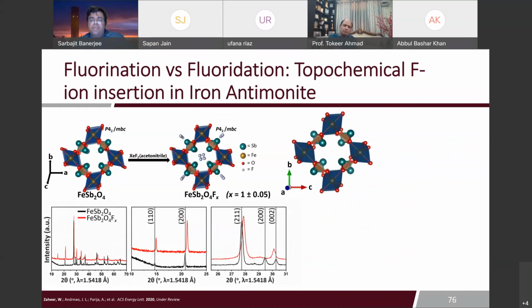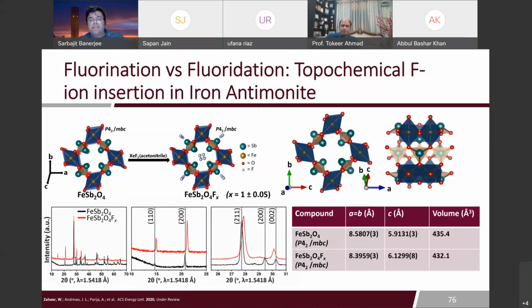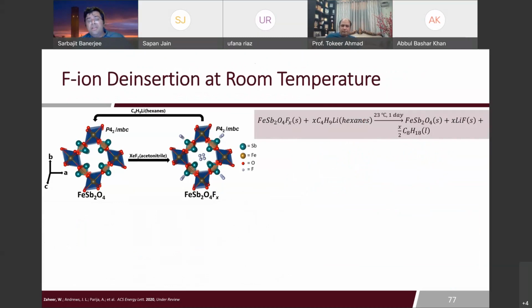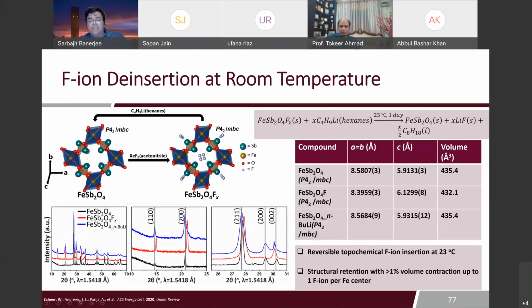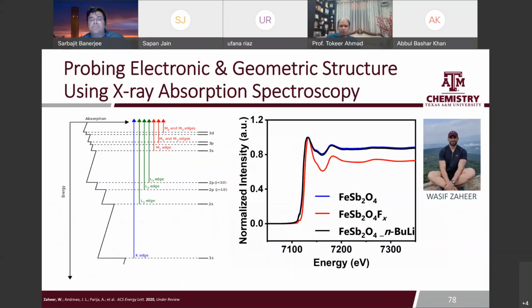So what happens here is again the exact opposite of a lithium-ion battery. Lithium ion coming into a cathode will bring about reduction, for instance, of cobalt. Here, the fluoride ion coming into the intercalation host actually brings about an oxidation of iron from 2+ to 3+, and slight expansion. This is work we've done. There are still not very good fluoride ion electrolytes available, but we can do a reaction with xenon difluoride, for instance, and then we can defluoridate as well, and do reversible fluoride ion insertion. What we're really happy about is that we can do this at room temperature. We don't need high temperature. We can do this entirely at room temperature.